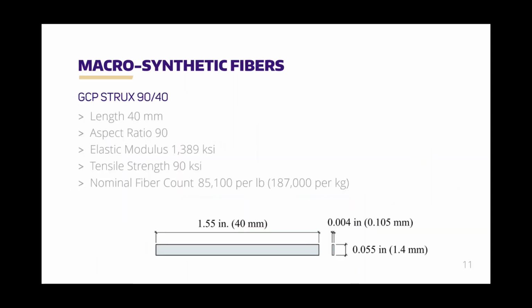The type of fibers that we were using in this test series are GCP Strux 90/40. They have a long track record of use in both experimental testing and also in practice, and because they had that track record, they were useful for our purposes. They're 40 millimeters in length, and have an effective aspect ratio of 90. You can see the dimensions there on the bottom. They're essentially a tape-like fiber with a high elastic modulus and tensile strength. So that's why they were quite useful for this test.